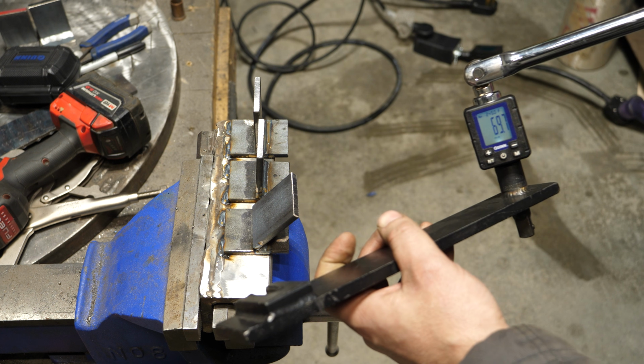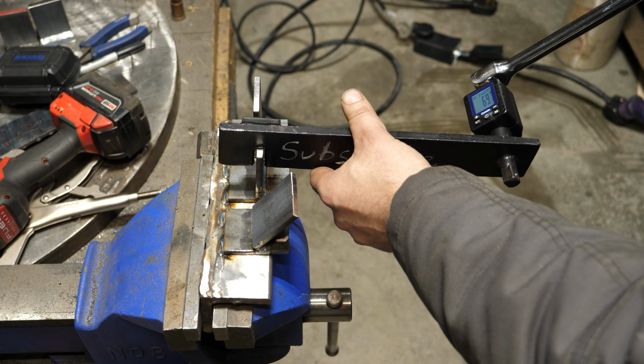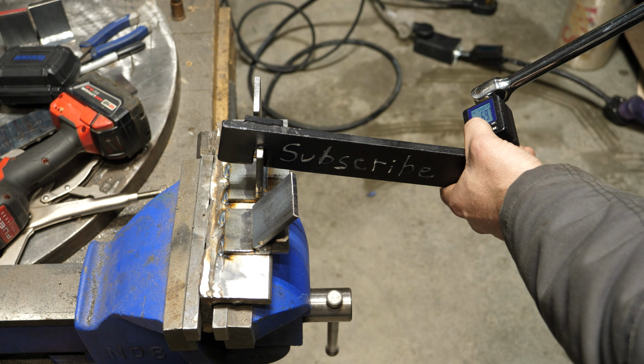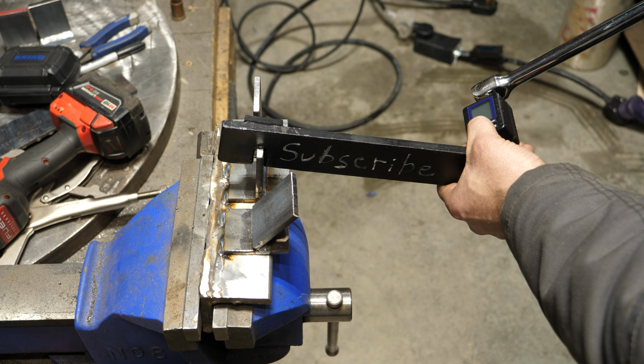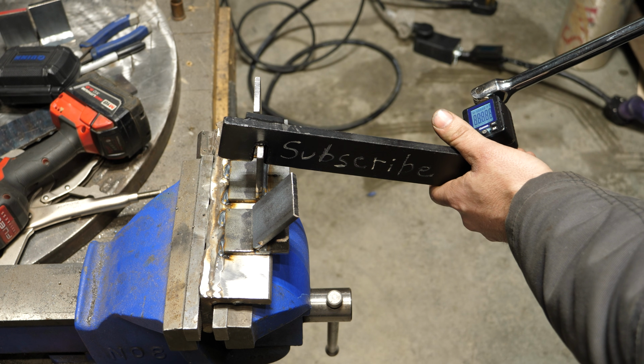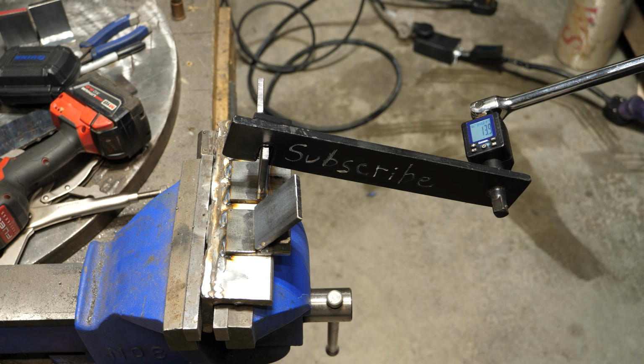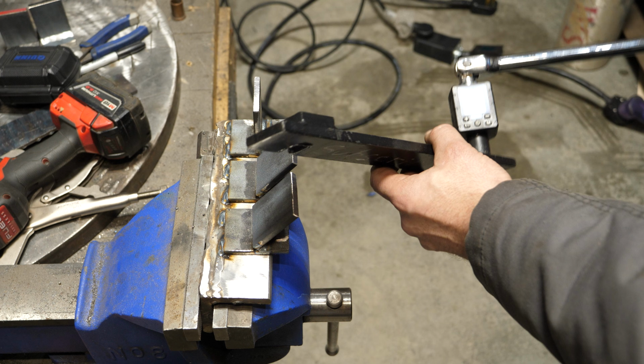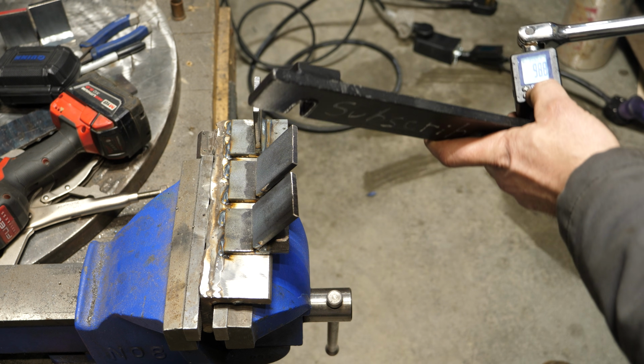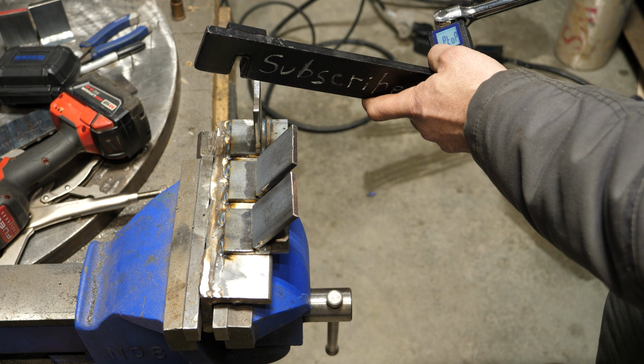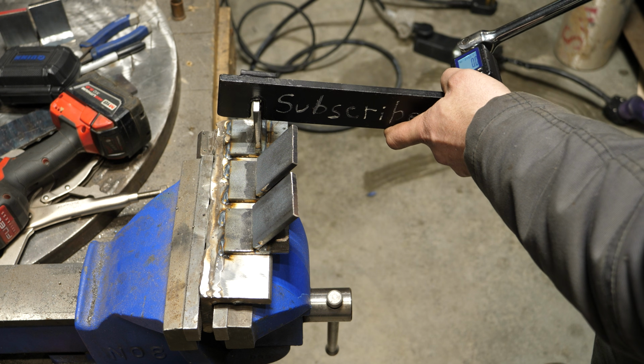So 69 foot-pounds, which that's not necessarily out of the ordinary. I guess this is 1/4-inch plate, but we'll find out if there's differences. And that was straight in. This is push. And 98, so that's pretty typical, I would say. So the straight in definitely was weaker, which my prediction is it had poorer fusion in the root. Now let's look at the pull.